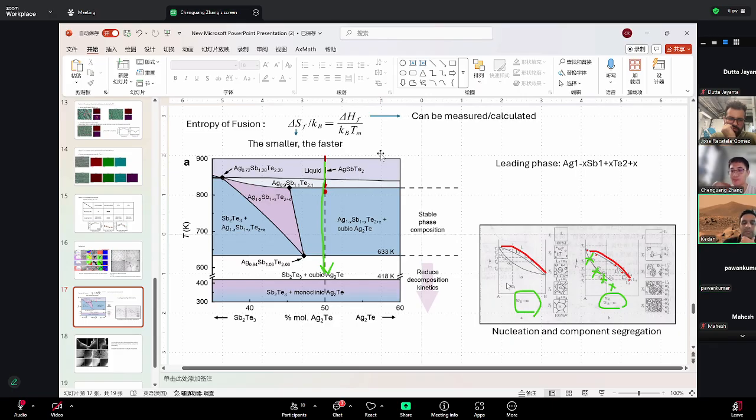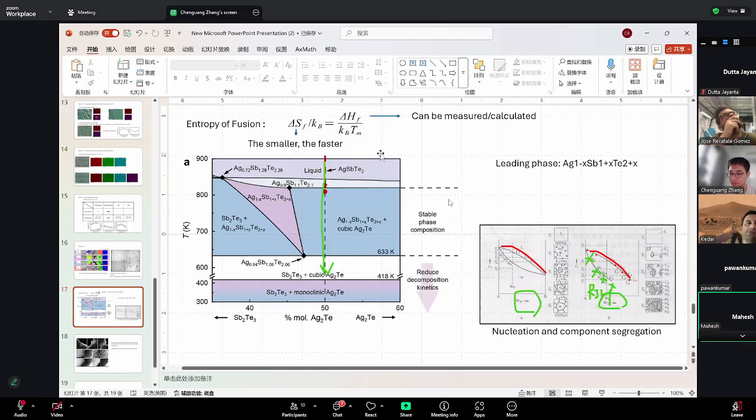We have thermodynamic. How do you compare the rapid Joule heating? The whole idea here is that the green is rapid Joule heating, right? Rapid Joule heating, yes. And then the cooling rate is much faster. This is rapid Joule heating, which is the rapid cooling rate, and then this is the slow cooling rate, which is the thermodynamics. You need to have different quenching rates at the XRD stage. You literally need to freeze your reaction at those intermediate temperatures when you're cooling. How do you do that?